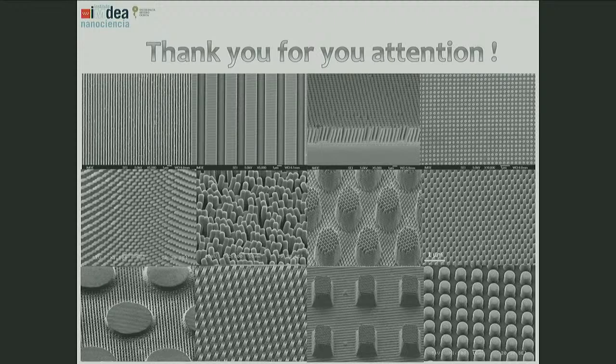Yeah. So it depends on what you start with. The material properties definitely determine the function and the final property. In terms of biological materials in nature, for insects and so on, most of the materials are proteins that are slightly hydrophobic. So that's why most of the insects are hydrophobic, self-cleaning, nothing sticks to them. There are keratin, alpha keratin, some kind of protein material, and chitin. They're actually more resistant materials than thermoplastics like polypropylene, polystyrene. They are much more expensive, so that's why we don't use them all the time, but actually the properties are very good.